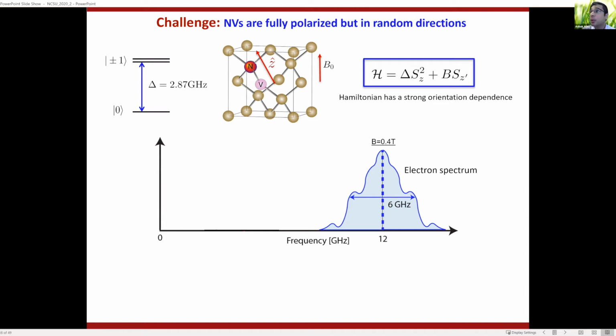So instead, what we want to do is to take all the carbons which are in the diamond and align them all in one direction. So you've got these NV centers which are polarized all in random directions. If you have a microscope or a magnifying glass and you can go down into the lattice, you can see all the NV centers spin polarized, but they're polarized in random directions. And what we want to do is convert this order that exists at a nanoscopic length scale into magnetization of nuclei which are all in one direction.